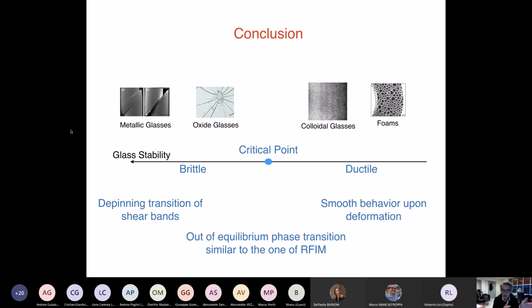And then there is the other thing, which I think is very interesting. In the case of the brittle behavior, I tried to argue from simulation and theory that this brittle behavior is due to the fact that somewhere in the system there is a region which is far more prone to fail, and this region is the seed for the shear band. Now, understanding the depinning of this seed and the creation of the shear band, I think it's an interesting depinning transition, but it's a depinning transition of a new kind.